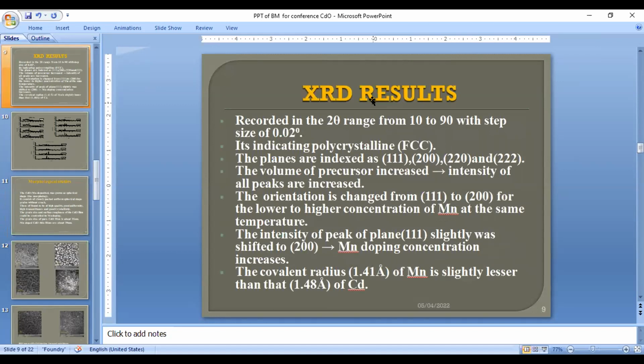So these are the results, the XRD results. The XRD results are recorded in the 2 theta range from 10 to 90 with a step size of 0.02 degrees. It indicates a polycrystalline FCC structure. The planes are indexed at the 111, 200, 220, and 222 planes. As the volume of the precursor is increased, as I already told, from 10 ml to 50 ml, the intensity of the peaks also increases. The orientation changes from 111 to 200 from lower to higher concentration of Mn at the same temperature. The optimum temperature is 250 degrees centigrade.